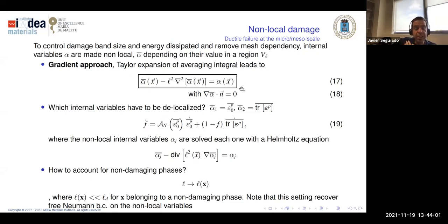This is the equation, and this equation is saying, imagine that alpha is the porosity or any local state of the material. It can be the plastic strain or the porosity or whatever. What we're obtaining with this equation is like a non-local version, so an average version. And this average version is a solution of this partial differential equation. So input is alpha, output is alpha averaged, and this L is the characteristic length. The characteristic length means the influence of the nearby points. If L tends to 0, we recover the original model,